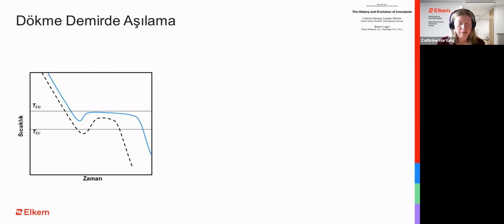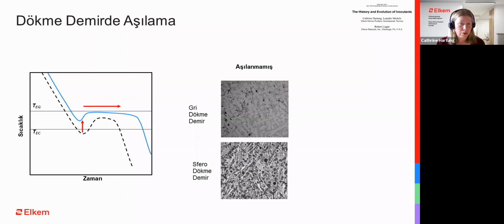So if you press again, you see the vertical arrow represents the T_EC, and you see that the inoculation lifts the curve. So instead of having solidification starting below the metastable line, the solidification is now starting between the lines. The other part that inoculation does is that it gives you a longer curve, so you have more carbon coming out as graphite when you inoculate compared to when you don't inoculate. I should say that the blue line represents inoculated, while the black dotted line here represents the uninoculated condition.